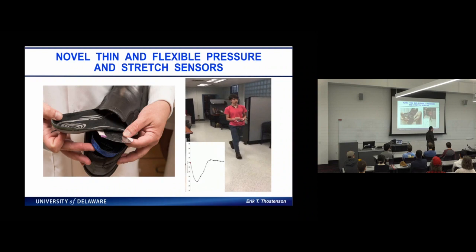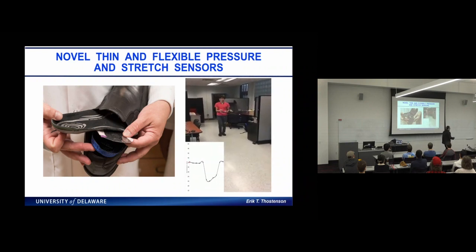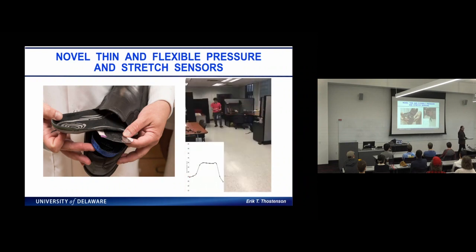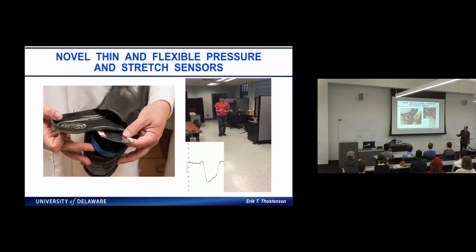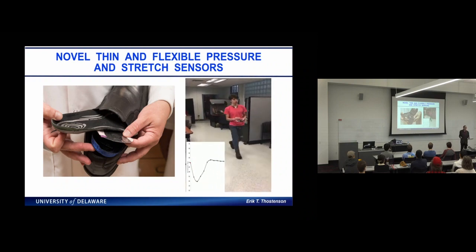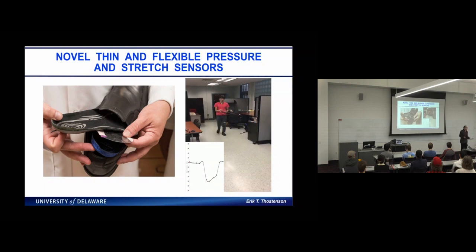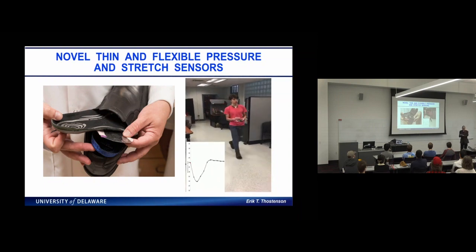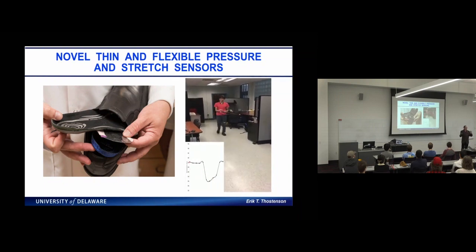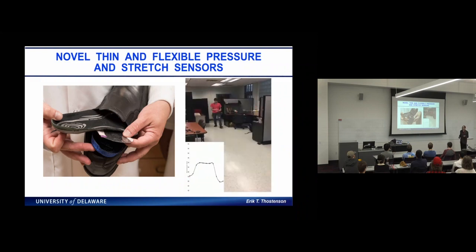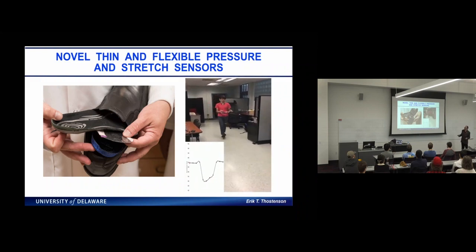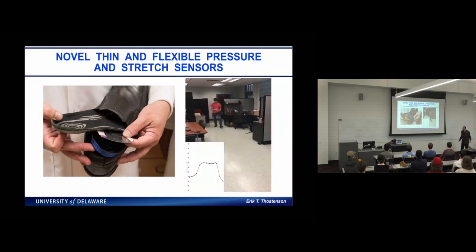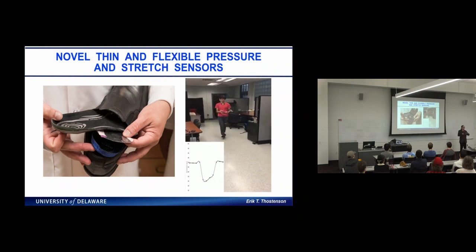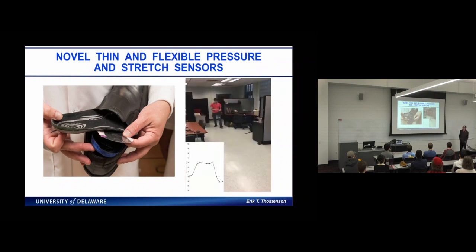But the idea here was that we had actually developed these unique sensors. And this is just an example. This is the same type of sensor that's on the bridge. It's actually a non-woven fabric. We use an aramid fabric, but we can use a lot of different types of fabric. And you can see those are the shoes I'm wearing today, and it slips right into the insole.